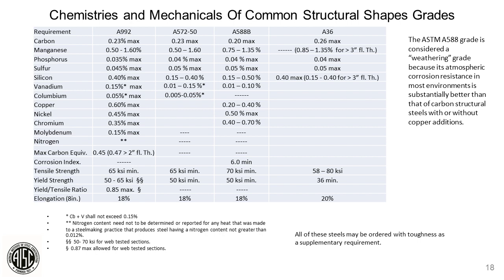So how does this all pertain to the engineer that's looking at his MTR? Again, we live and breathe by this in our world, but the top requirement here, kind of give you a table looking at the different things. A little bit busy. It looks complicated, but really it's not. There's only certain key elements that you need to understand and focus on, and we'll go through those as we go through the processing later. But ASTM A992, the typical wide flange structural steel grade, A572 Grade 50, you'll see that. You've got the A588 Grade B. Thank you, Brent. And then, of course, A36, the old standby. As you go down to the next line of the table, we start talking about carbon. If you look at those, they're fairly consistent. It's got 0.23 carbon max. So the spec allows us to go higher.